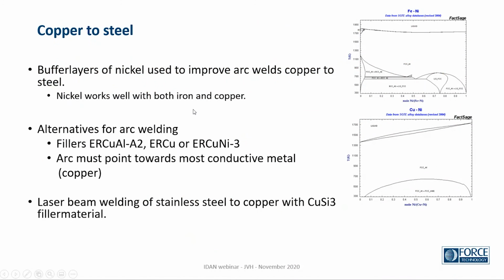An example of using nickel as a buffer layer when you are welding copper to steel. Nickel would be fully weldable to the steel side and also to the copper side. So if we buffer the steel with nickel, or both steel and copper, and then make a joint with the nickel in between, then we can join these materials.